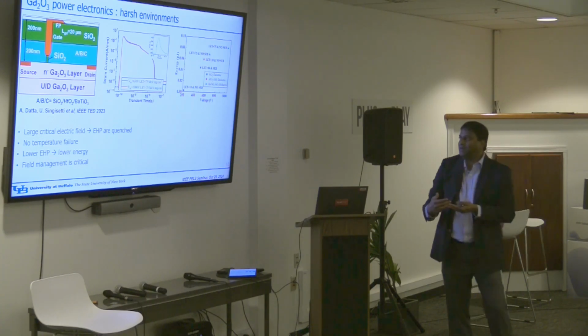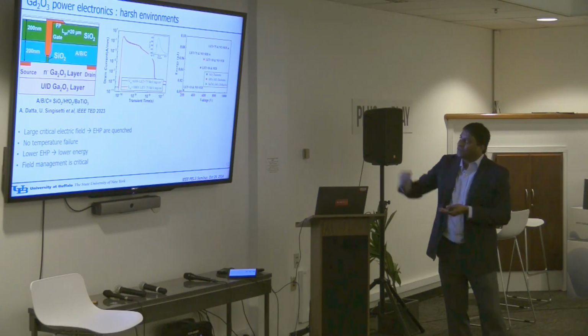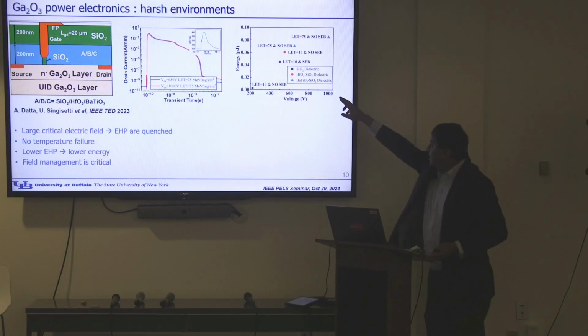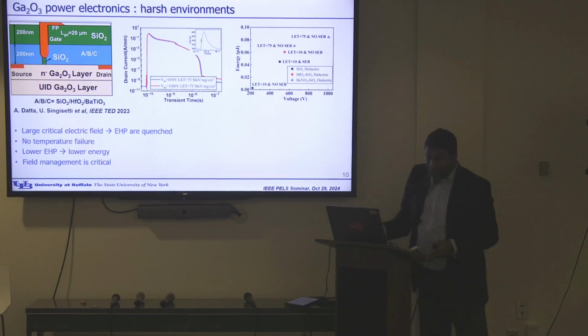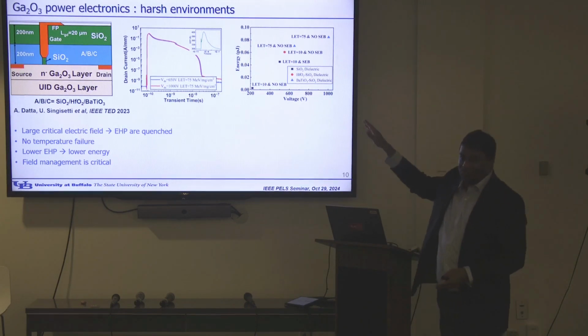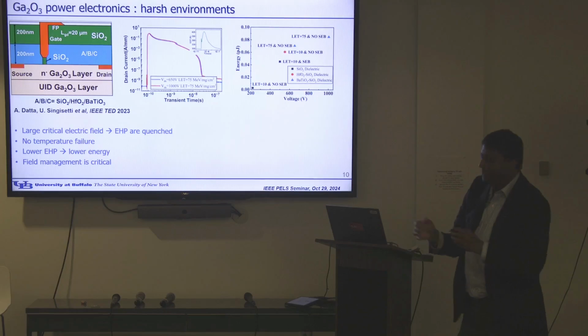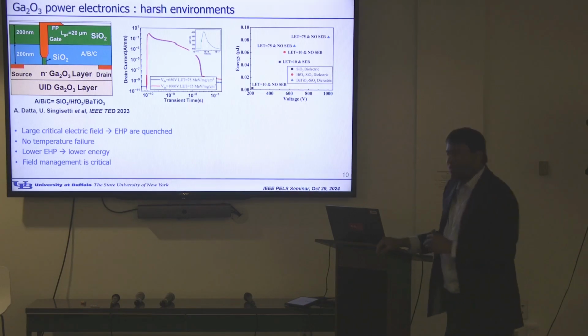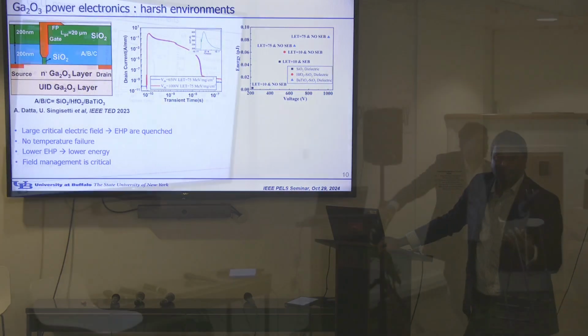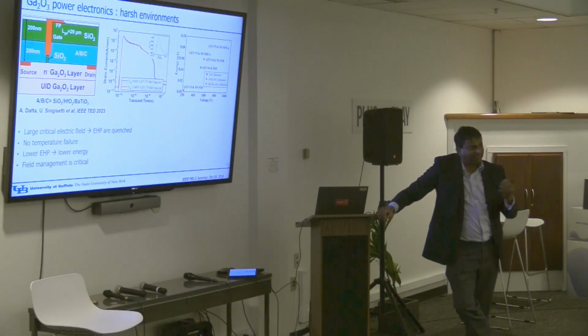Usually in a power semiconductor. Surprisingly, it did not fail thermally, right? So in this particular example, when you look at the thermal behavior, it did not fail thermally actually. It was just an electrical failure, right? Which is kind of counterintuitive, right? Because gallium oxide has low thermal conductivity, it doesn't make sense.